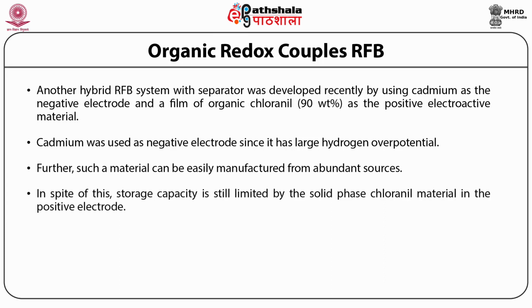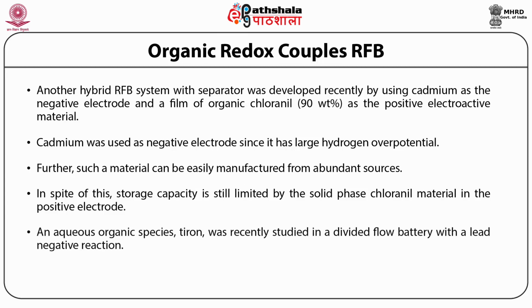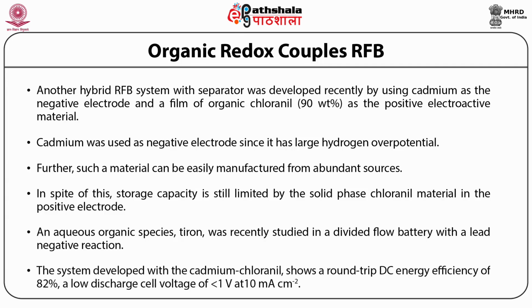In spite of this, storage capacity is still limited by the solid phase chloranil material in the positive electrode. An aqueous organic species, Tiron, was recently studied in a divided flow battery with a lead negative reaction. The system developed with the cadmium chloranil shows a round-trip DC energy efficiency of 82%, a low discharge cell voltage of less than 1 volt at 10 milliampere per centimeter square.